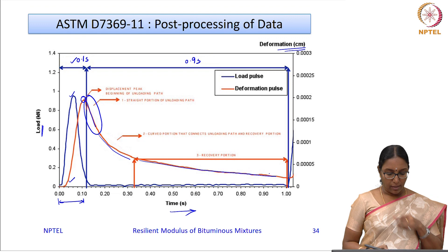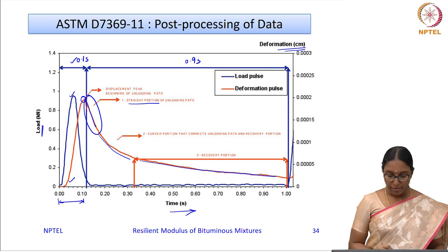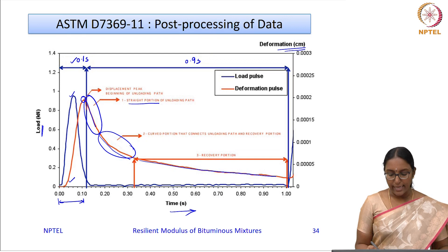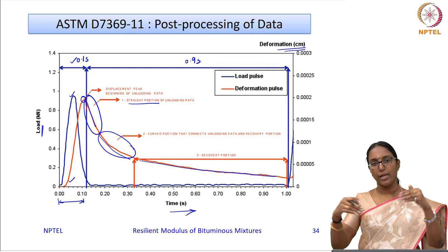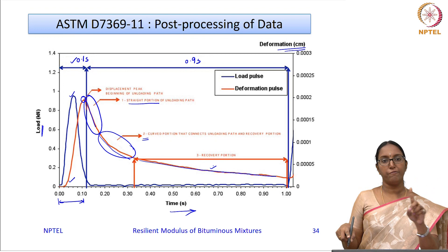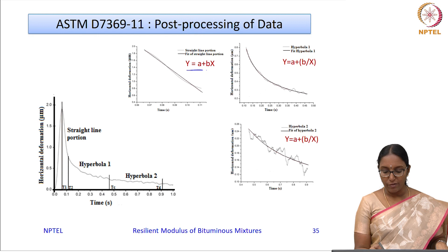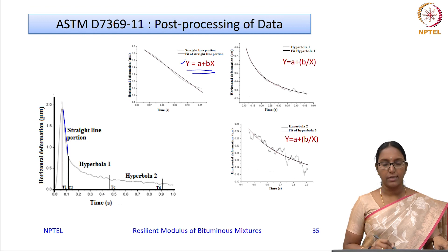Three different curves can be fitted to the recovery portion. In the first region, a straight line is fitted. A straight line equation of the form y = a + bx is used, where y is the deformation, x is the time, and a and b are regression coefficients. This straight-line portion covers the initial recovery during unloading.